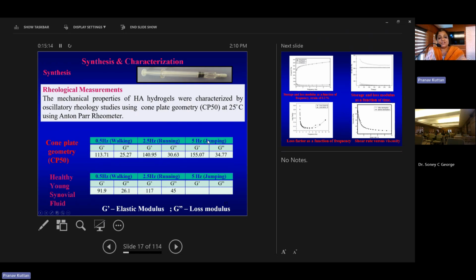And this is actually a comparison of the rheological parameters with the healthy young synovial fluid present in humans. That is three different frequencies we have compared. That is walking frequency, 0.5 hertz, 2.5 hertz running frequency, and 5 hertz, that is jumping frequency. So we tried different formulations and we could come up with a hydrogel which is almost matching with the healthy young synovial fluid, and we optimized that formulation.